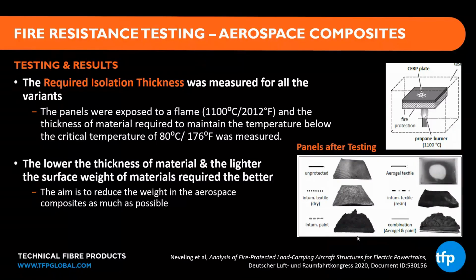You've now reached the glass transition temperatures of the resin systems and some of the components that will break down and degrade. If you look at the photos, the panels after testing photo on the bottom right, you can see the blank, the unprotected. The next would be an aerogel textile. Then they also used our product as both a dry form intumescent textile and with a resin system. They looked at an intumescent paint, and the last photo was the combination of the aerogel and the paint. They were really shooting for a very low thickness of material to survive that critical 80 C temperature range. Next slide, please.